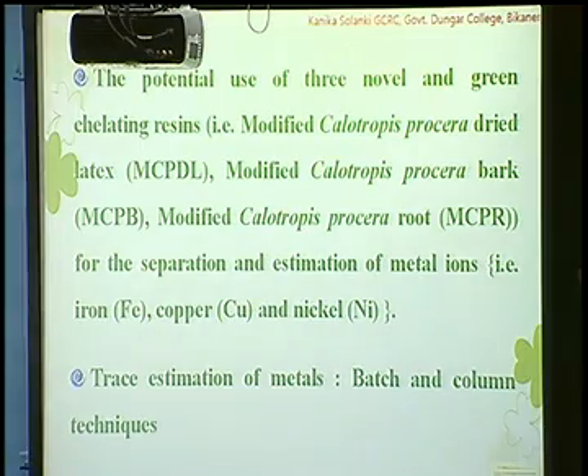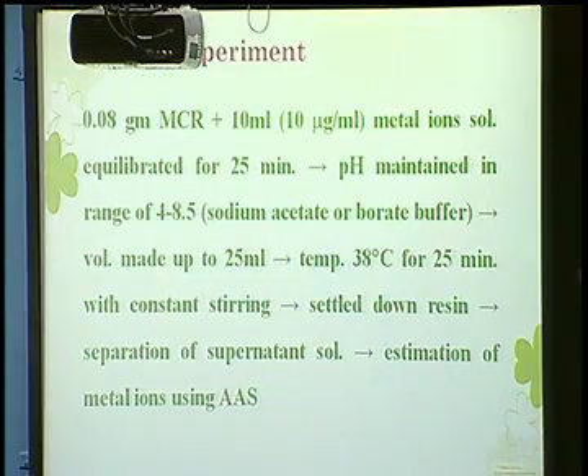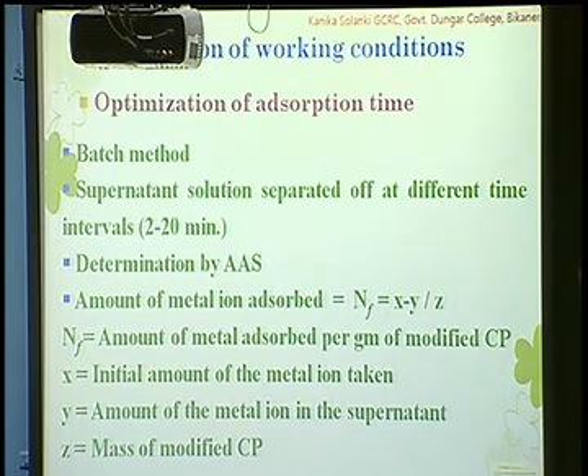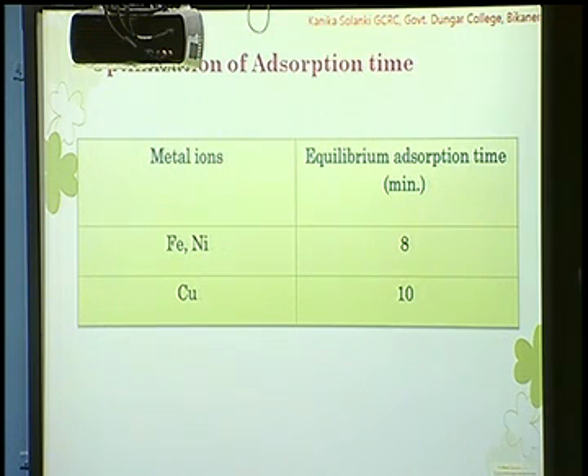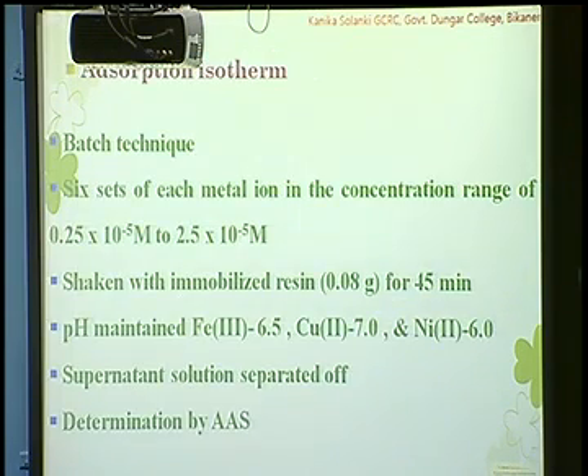For the trace estimation of metal ions, we have used batch and column method. The optimization of working condition: for the optimization of absorption time, we have used batch method, and the supernatant solution was separated off at different time intervals between 2 to 20 minutes, and the solution was determined by means of AAS. As you can see in the table, the equilibrium absorption time for ferrous and nickel is 8 minutes, and for copper it is 10 minutes. For the absorption isotherm, again the batch method is used, 6 sets have been prepared in the range of concentration, pH was maintained, and the supernatant solution was determined by AAS.